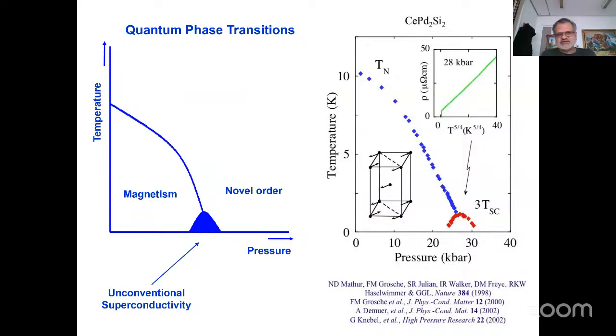So going back to the science a little bit and reminding you of the general phase diagram we discussed, and again a very initial result of how we can take a magnetically ordered system, in this case cerium palladium silicon, apply pressure, and thus tune its Néel temperature down towards the critical point, which is interrupted by the emergence of superconductivity. And here there are two things to note, which will feature later.